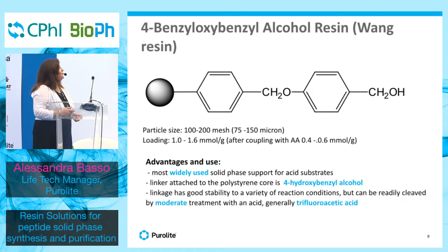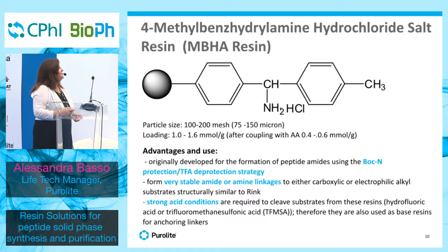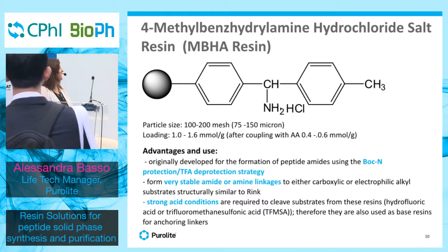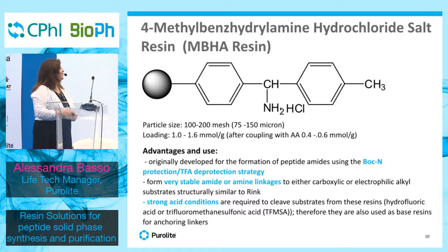The last resin will be the MBHA resin. It's a resin with this kind of linker that is for the Boc chemistry this time, and it has a very stable amide or amine linkage. You need, in this case, very strong acid conditions to cleave the substrates.